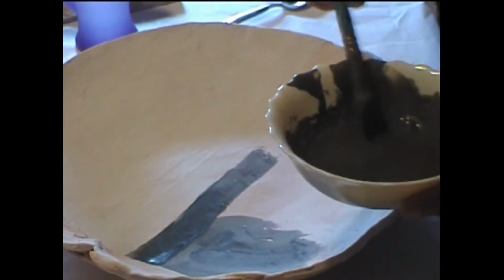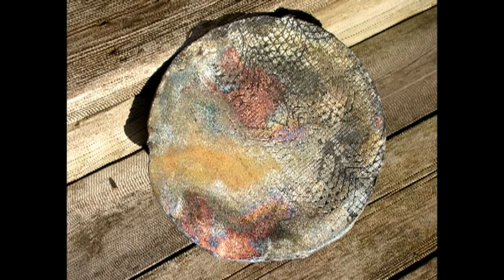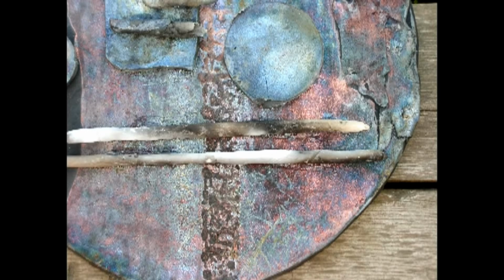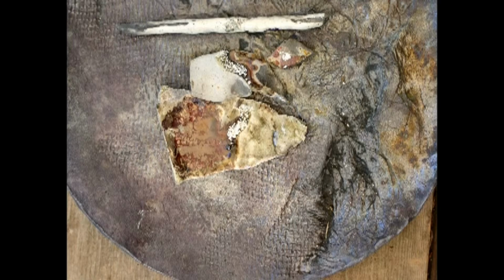The exciting colors they develop during the raku firing process are the result of oxides or metallic substances that are put within the glaze, and they're usually in high saturation levels. One of the main of these is copper carbonate. The copper carbonate is what gives you the bright metallic copperish colors, as well as many reds, but also greens. If you are using low concentrations of copper carbonate and firing in the proper atmosphere, you would get more greens.